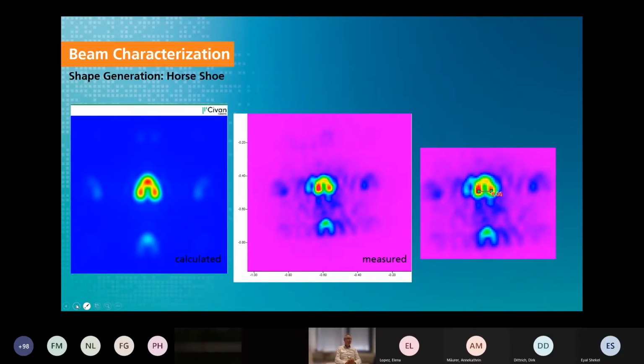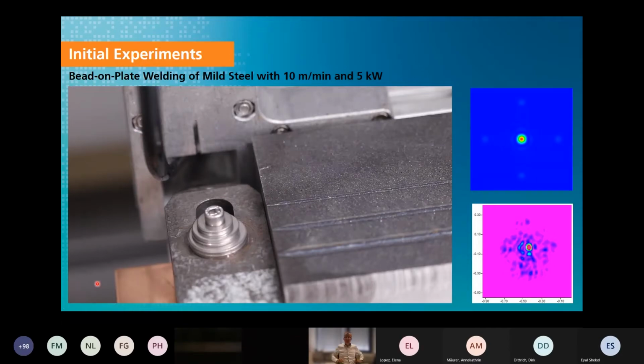So on the next slide, I have another example. We have programmed a so-called horseshoe. Here on the left-hand side, you can see what the calculation is saying, and on the right-hand side, you can see what we have got after passing the focusing lens in the focus position. The distance between the two peaks programmed in the horseshoe is 60 microns. Once we characterized the power distribution, we got a good feeling of what to expect.